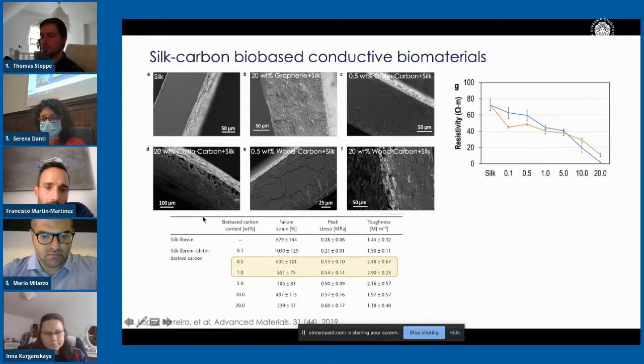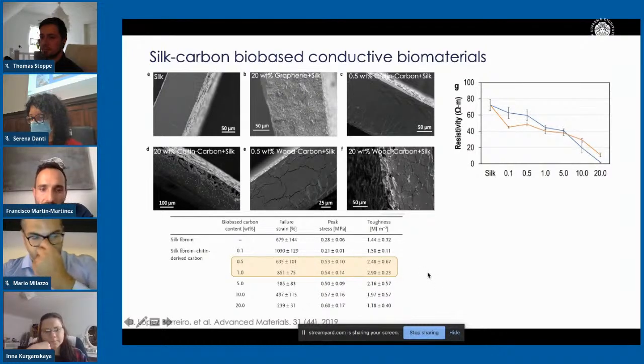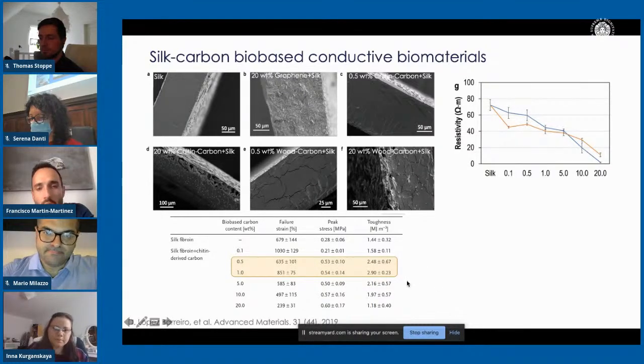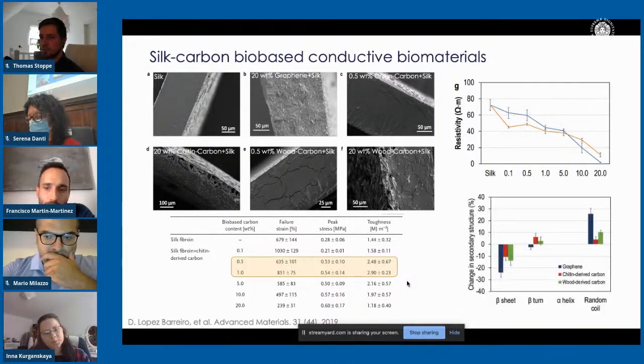And then when it comes to mechanical properties, there is an increment also in the failure strain. The peak stress and toughness go up and then go down as you increase the percentage of bio-based carbon. There is a sweet spot here, with 0.5 or 1, where you have lower resistivity, higher failure strain, and higher peak stress and toughness. So you have better mechanical performance and higher conductivity.